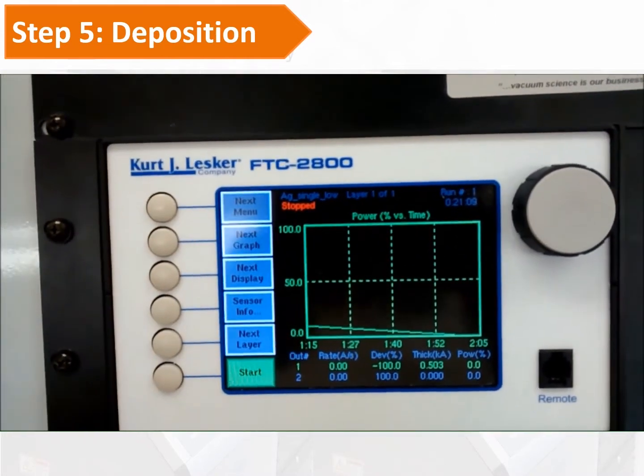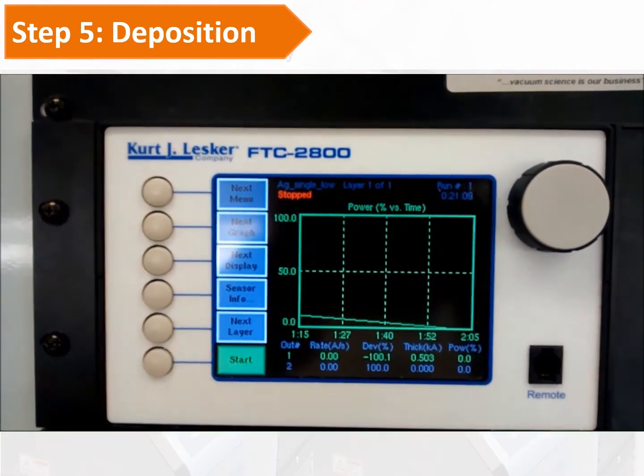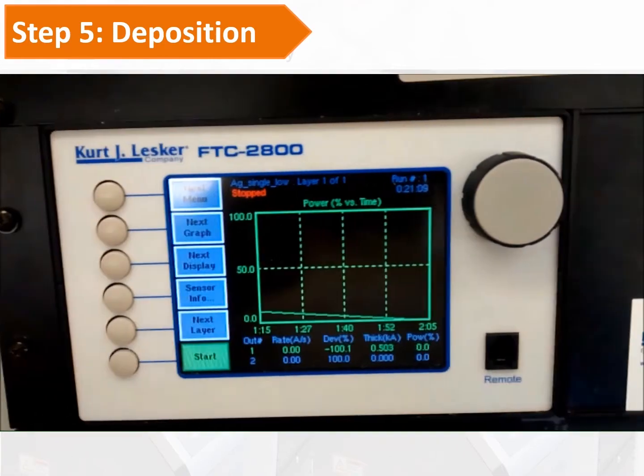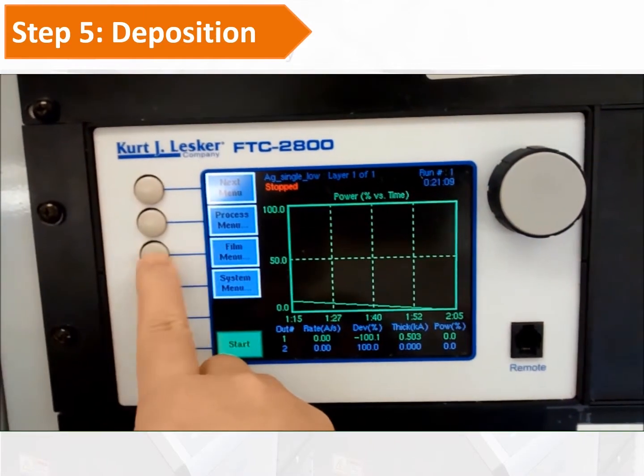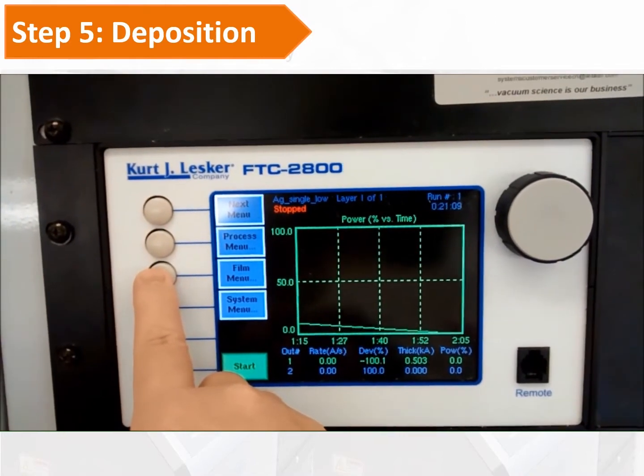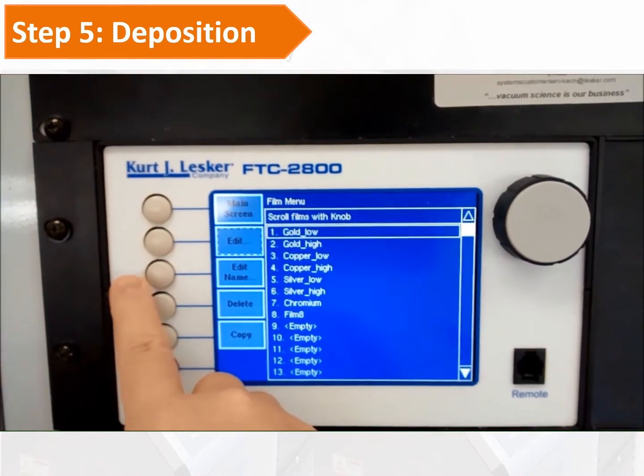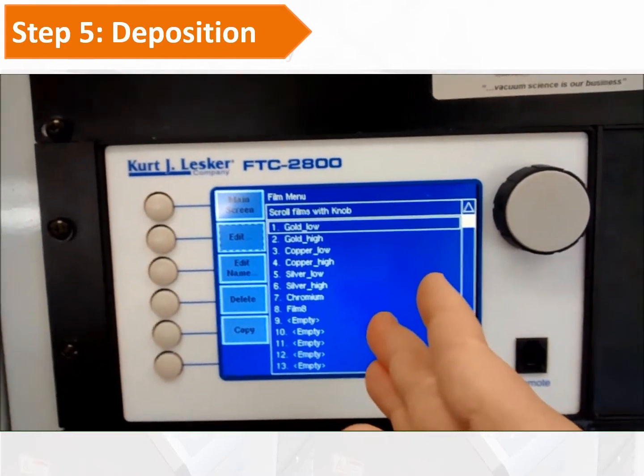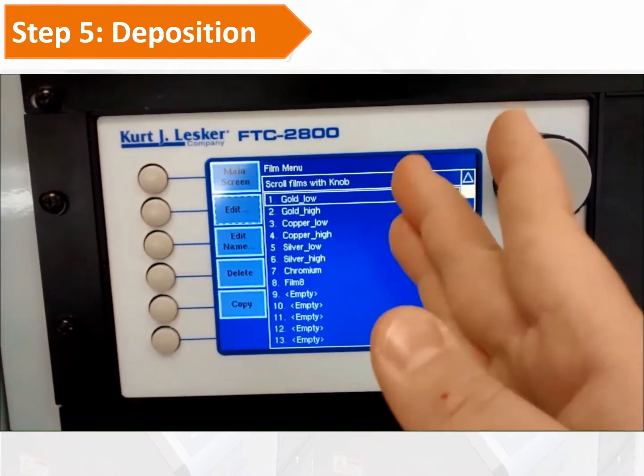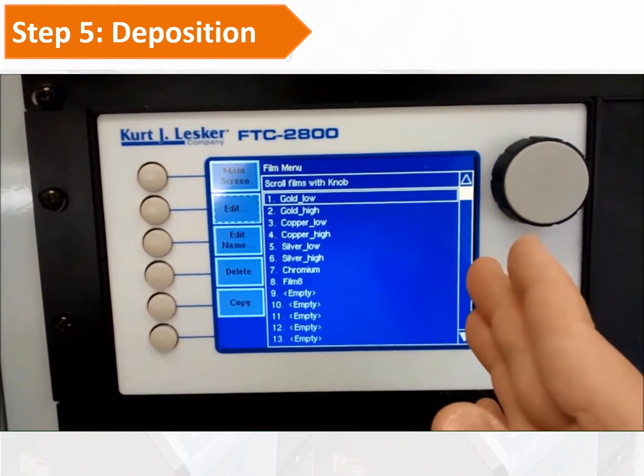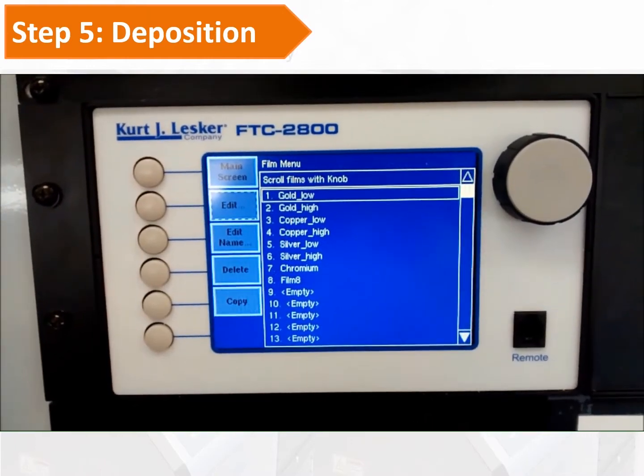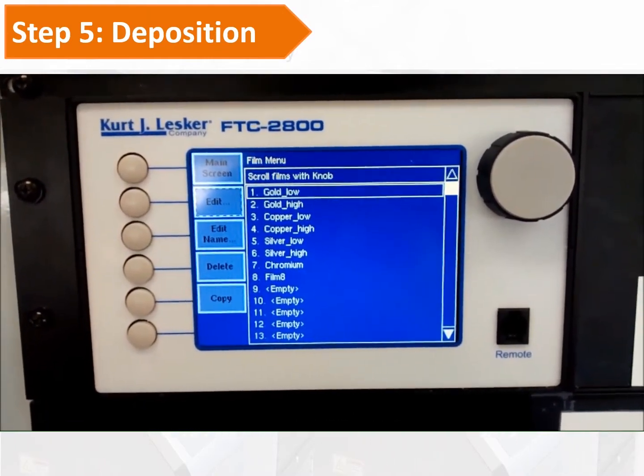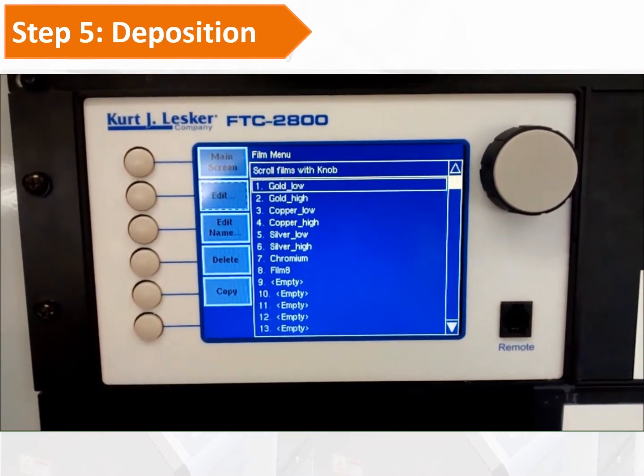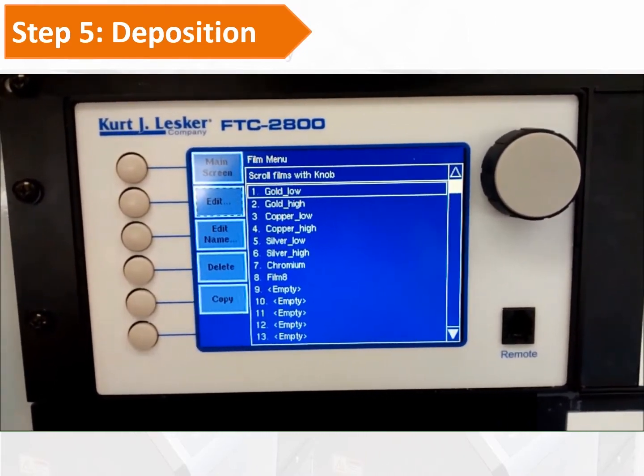First, we want to add the source pocket number in the film menu. Press the next menu until you find the film menu shown on the screen, and then press the film menu. You will find there are low and high recipes for gold, silver, and copper. It has only one recipe for chromium. If your deposition thickness is less than 50 nanometers, choose the low recipe. If the thickness is more than 50 nanometers, you can choose the high recipe. Chromium is really used as an adhesion layer, so we just have one recipe for chromium.